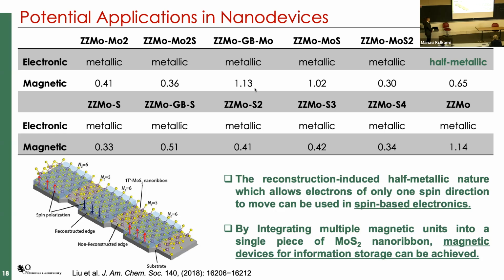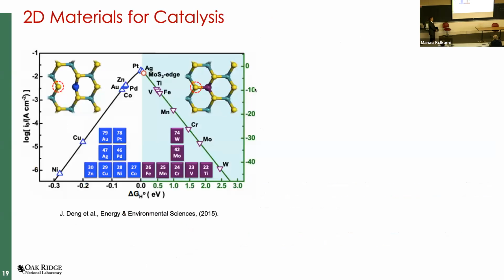There's an interesting paper published not too long ago, but basically this says if you can transform the edge of these 2D materials, and they're thinking about making single atomic thick transistors, how you can change that to have different properties. So spin polarization, for example, how you can create heterostructures. Of course, this is a 1T prime phase for molybdenum instead of the 2H. But long story short, if you can change the structures, perhaps you can use this in future devices. And so some of the things that we're thinking about right now targeting is spintronic applications or even magnetic storage media, how you can change the local properties. And I'll get to that in a second.